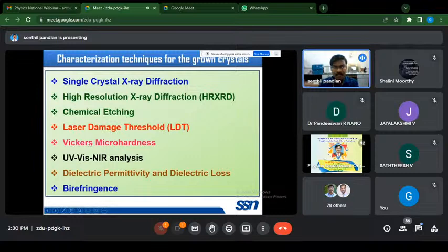For laser application, one must know the laser damage threshold value of the grown crystal, and we carried out the single and multi-shot laser damage threshold measurement at IISc Bangalore. In order to identify the mechanical stability of the grown crystal, we carried out the Vickers microhardness measurement.